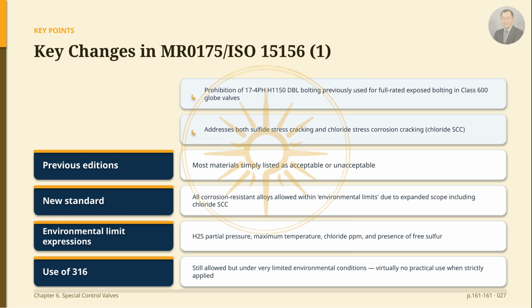I'll introduce the major changes in MR0175/ISO 15156. First, 17-4 pH H1150 DBL bolting, which was previously used for full-rated exposed bolting in a Class 600 globe valve, is no longer allowed. Second, this revision addresses both sulfide stress cracking and chloride stress corrosion. Prior versions simply listed most materials as acceptable or unacceptable. However, as the scope expanded to cover chloride stress corrosion, the new standard changed to allow all corrosion-resistant alloys within certain limits, referred to as environmental limits or environmental restrictions.